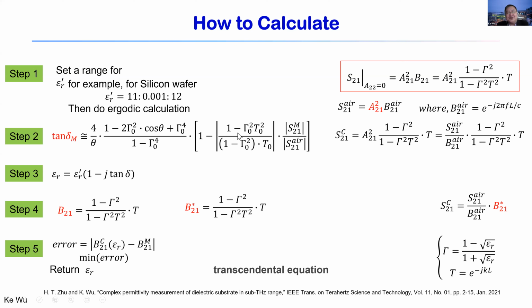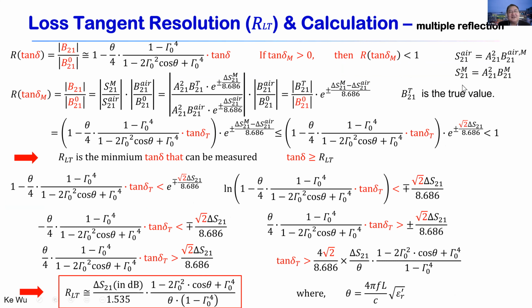So this is a very interesting solution which gives us highly accurate parameters. I will show that a little bit later on. And of course, these procedures can be tested through multiple levels of calculations. We call it the ergodic calculations. These procedures are iterative, such that finally we're able to get the final results through this process. I will not go through the detail, because these equations involve a nonlinear process. It's a nonlinear equation. That's why we have to go through this iterative searching for solutions. So this is the detail of that loss tangent resolution.